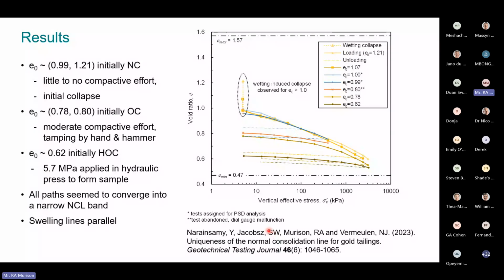The void ratio between 1 and 1.2 was considered initially normally consolidated, again because these samples had little to no compactive effort required in order to form them, and they exhibited initial collapse, as we see over here, meaning that they were in an initially metastable state. Samples at a void ratio of approximately 0.8 were overconsolidated. They required some moderate compactive effort that could be done by hand, but it required a tamper and a hammer. And finally, our sample at a void ratio of about 0.6 was definitely heavily overconsolidated. We needed a hydraulic press to form the sample, and we compressed it with 2.6 tons of force, or 5.7 MPa. So definitely overconsolidated with a big stress history initially.